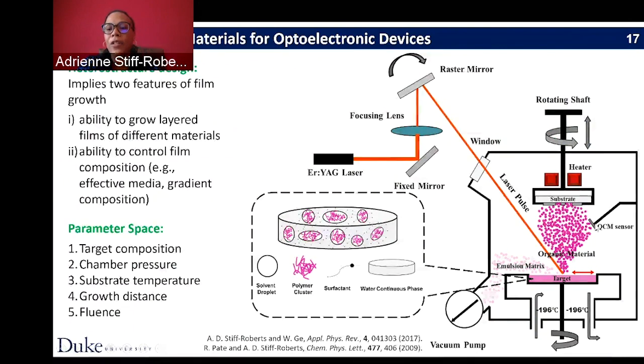But this is just a schematic diagram showing the process that I mentioned. So we have this erbium-YAG laser, it's infrared, it goes through a rastering system. We have the target that's cooled by liquid nitrogen, and this target cup is rotating, and as it rotates, the laser rasters back and forth so that you're getting coverage, irradiation of the laser across the entire target surface. And then per laser pulse, you're sublimating the matrix. When it does that, you're transferring kinetic energy to these emulsified particles that are within the target. And they get released to form a plume, and they intersect with the substrate to deposit the film. And so a lot of our work has been understanding, describing and controlling this process.